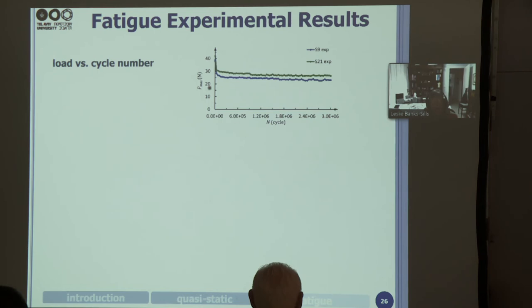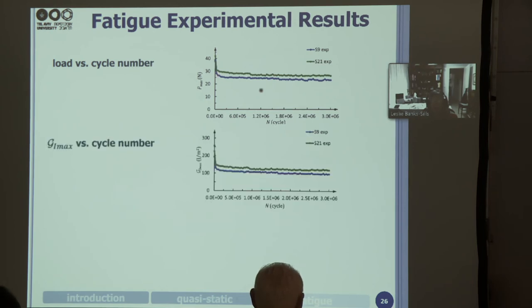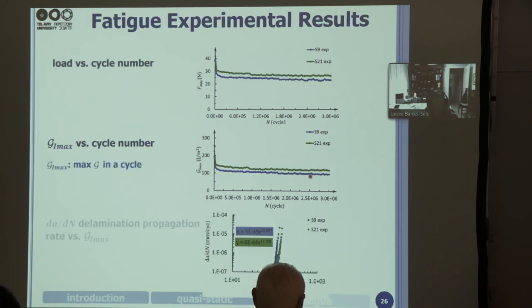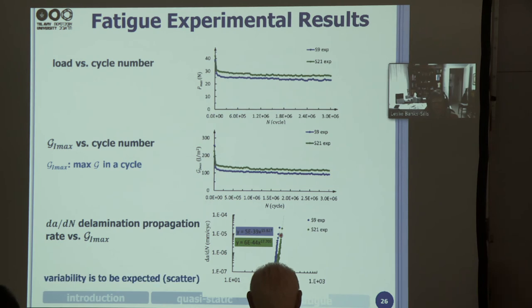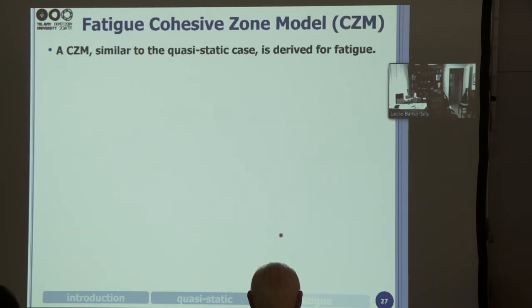And if we plot Pmax versus the cycle number for the two tests, this is what we see. And if we plot G1 max versus the cycle number for the two tests, we see they're not exactly the same, and we don't expect them to be because this is fatigue. And here we're plotting da/dN versus G1 max, and these are our two tests, and they're separated a bit because of the scatter in fatigue tests. So we expect this variability.